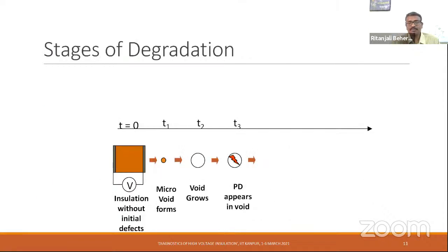These are the various stages of degradation of the insulation. At time t equal to 0, there is a virgin insulation without any initial defects. But under the influence of electric field, combined with physical, chemical and mechanical stresses, the micro void forms. This is the case with uniform field configurations. Even in that case, the formation of micro void is very much possible. And this void grows. Obviously, in the micro void, there are charged particles. The ionization takes place, and this gives rise to a bigger void.